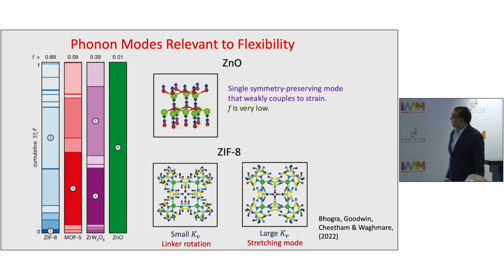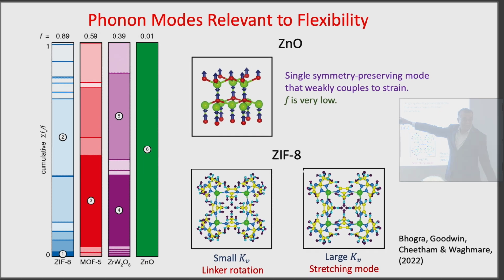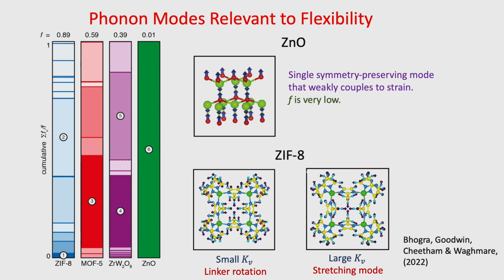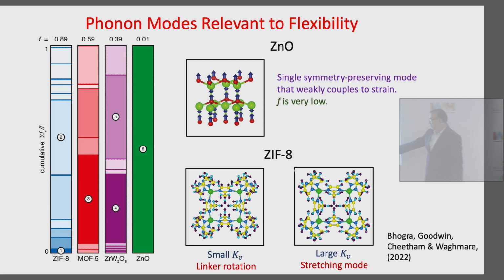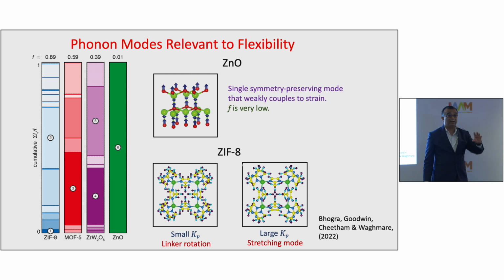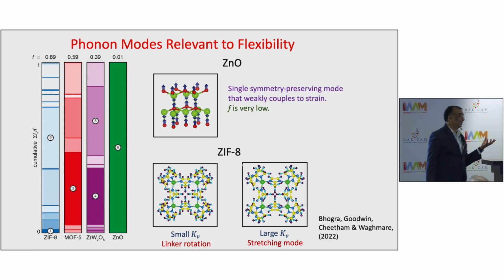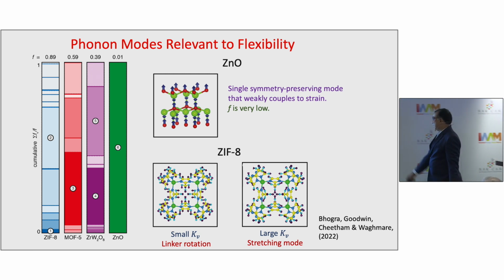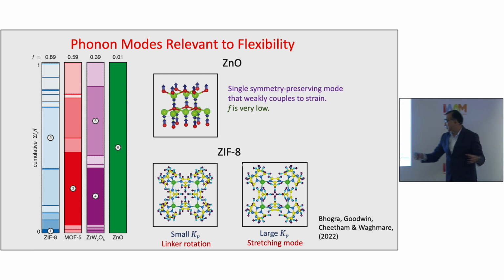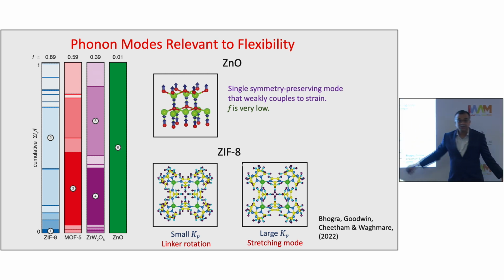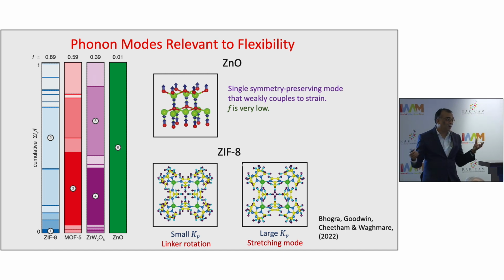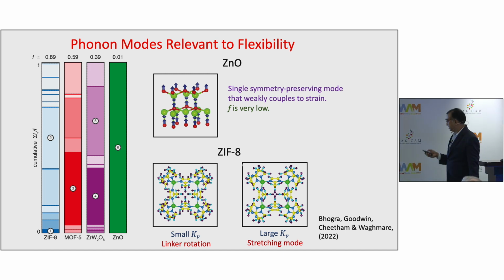Okay, so phonon modes relevant to flexibility in zinc oxide, you will see this is compressive flexibility, and this essentially involves different changes in the zinc and oxygen bond length, which are allowed by symmetry. And in ZIF8, there are many such displacements possible. The low frequency mode involves rotations of the linker. Rotations, of course, are very low frequency vibrational modes, whereas intermediate frequency modes involve stretching of these bonds, you can see here. Okay? And those are the ones which absorb all the elastic stresses that are applied to the system.